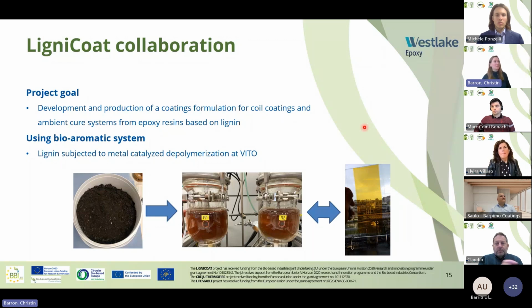So also from our side, the project goal is to develop and also to produce a coatings formulation for coil coating and also for ambient cure systems that are based on lignin. And then using these bioaromatic systems that we received from VITO, which you can see here on the left-hand side, very brownish solid material, we started our in-house process development on the 250 ml reactors in our labs in Pernis, Rotterdam. And when we are able to finalize these process settings and also having the whole analysis together, we send the material over to our colleagues in Duisburg of the product development and application. And you can even see the plant in the background. So they did the first tests and formulated different types of coatings.